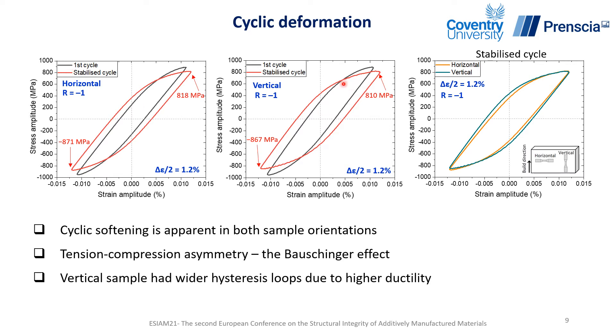This slide shows the cyclic deformation behavior of WAAM Ti-64 in horizontal and vertical orientations. By comparing the first cycle and the stabilized cycle hysteresis loop, it is apparent that this material shows cyclic softening behavior, which is generally observed in Ti-64 alloys. We have also noticed there is a small tension and compression asymmetry, also known as the Bauschinger effect, where the absolute tensile stress and absolute compression stress are not equal. When we looked at the stabilized cycle hysteresis loop between horizontal and vertical samples, the vertical sample had a wider hysteresis loop area, which is due to the higher ductility in this orientation.